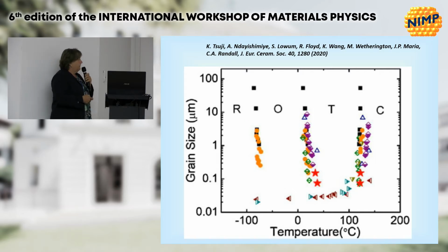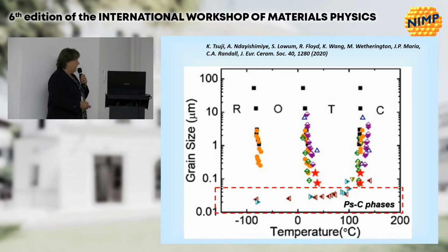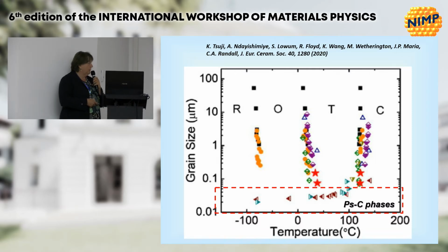A very interesting observation of this diagram is that fine grain sizes are described by so-called pseudocubic phases, because the distortion in all the phases, rhombohedral, orthorhombic or tetragonal, is quite low, and practically the system is almost cubic.